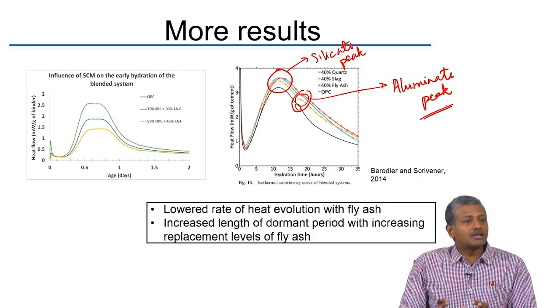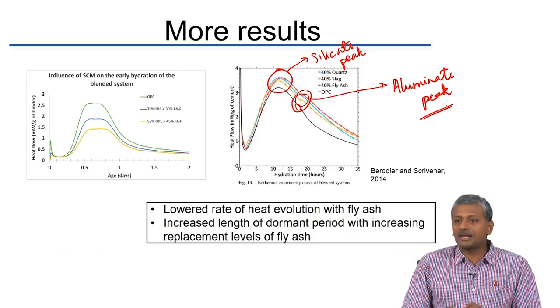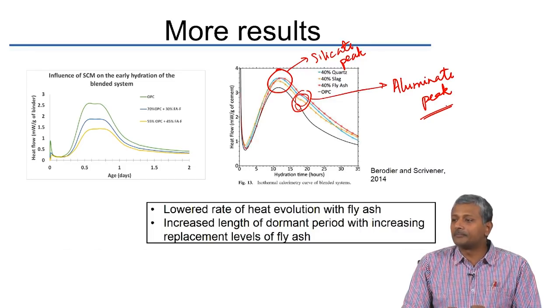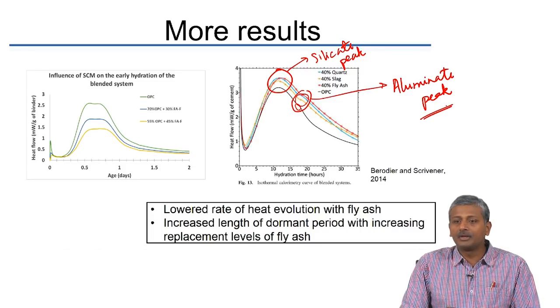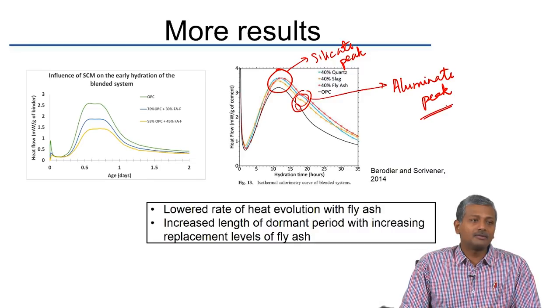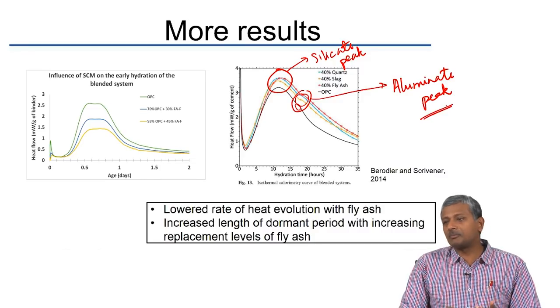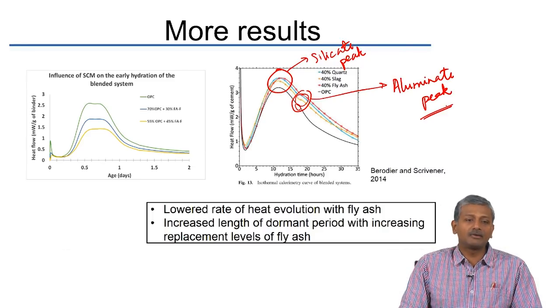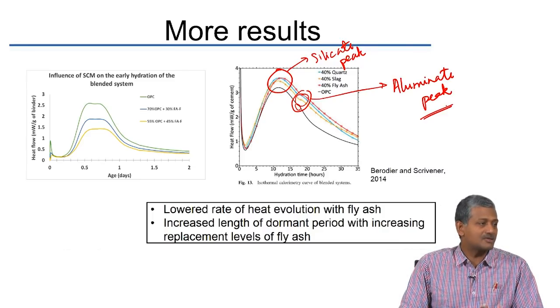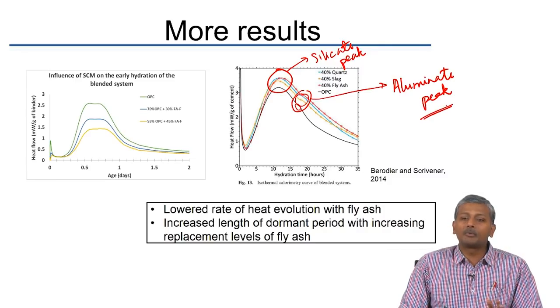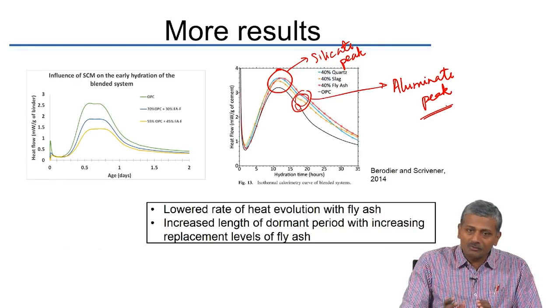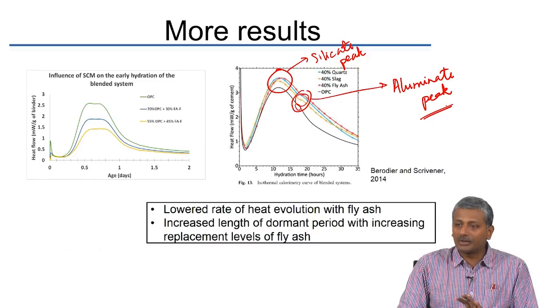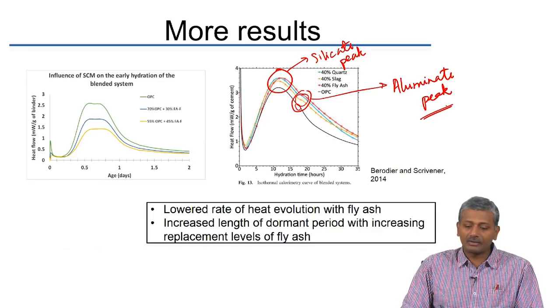This concern arises only with extremely reactive pozzolanic systems that have aluminates — specifically calcined clay, which gives a highly reactive aluminate system. In that case, extra care is needed to proportion sulphate well enough so that the aluminate peak always follows the silicate peak, ensuring normal strength attainment through silicate hydration.